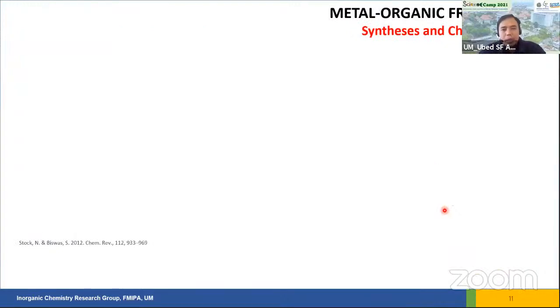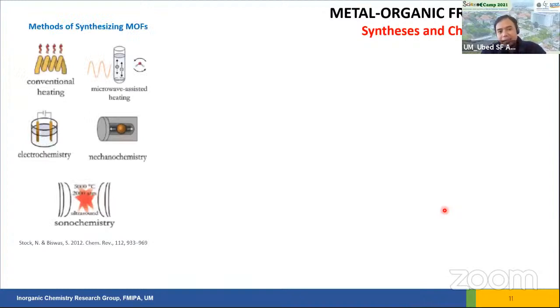So one of the most important things is how to make it. There are 5 methods in synthesizing metal organic frameworks. One is conventional heating. In principle, we need to react metal ions and the organic ligand, mix them, and then heat them, for example, in an oven. In a solvent, for example, we react zinc nitrate with terephthalic acid as the organic ligand, and the solvent is, for example, dimethylformamide or DMF, or we can also use water. Then put it in the oven using conventional heating, and after 1 day, you can see that the MOF is formed.